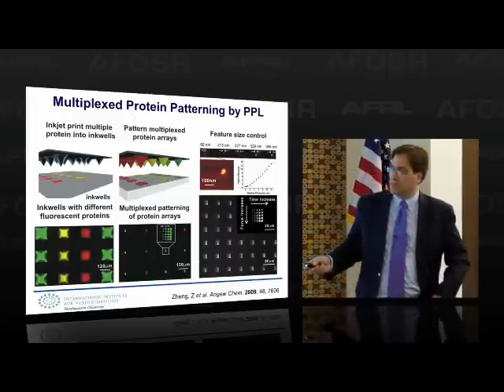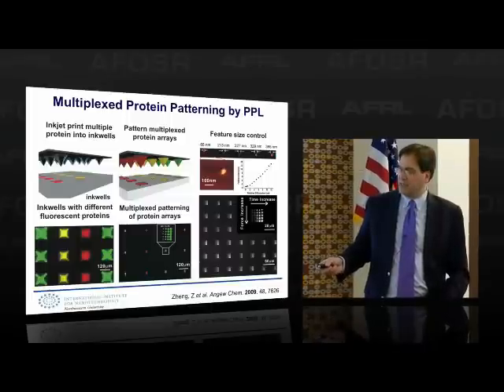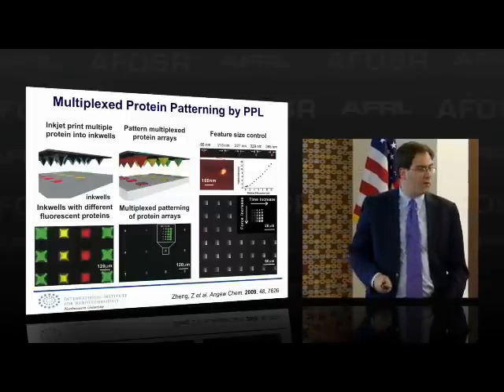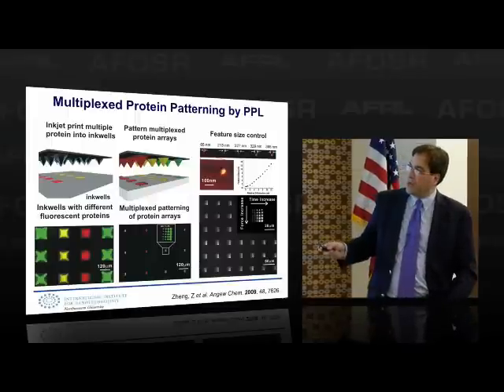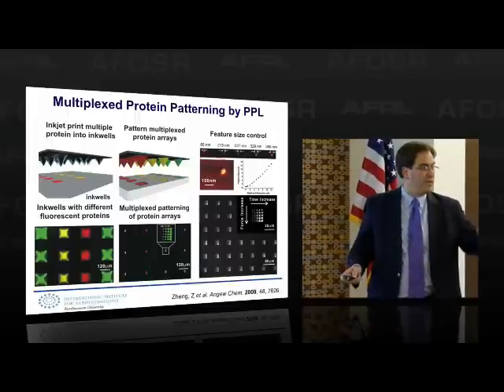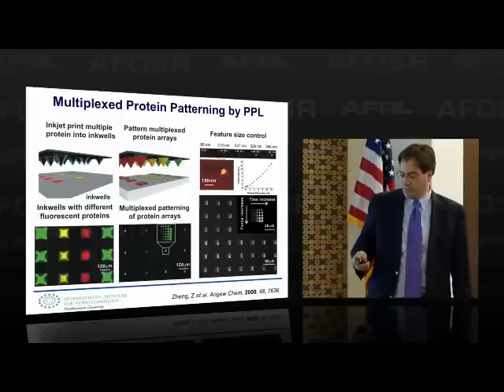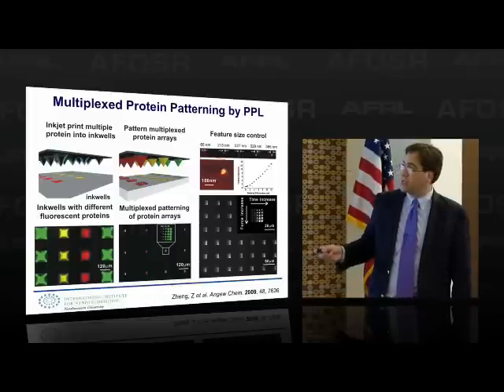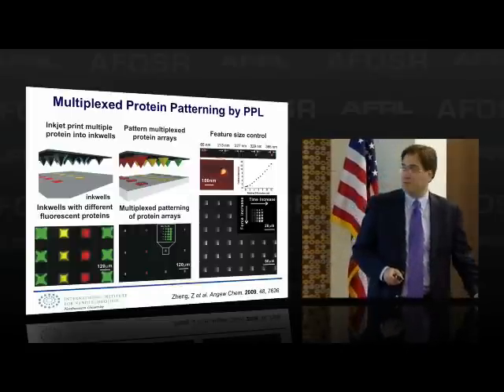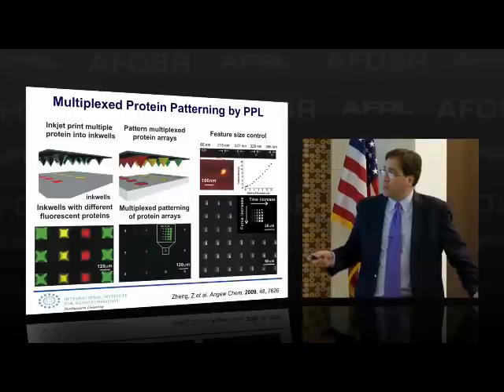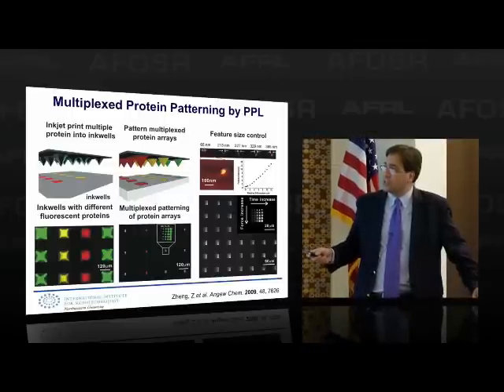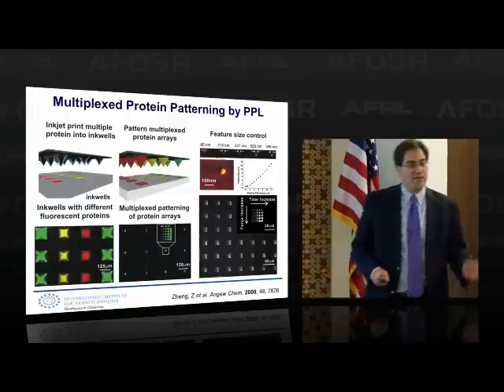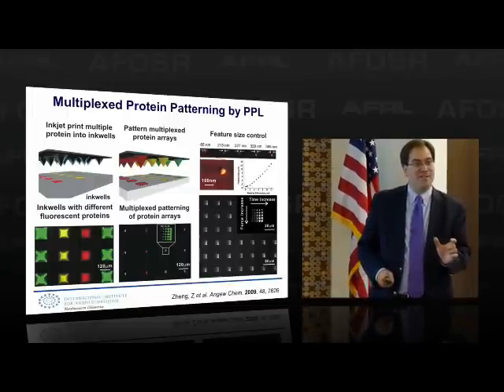We put dyes on proteins in this case, and even if you get a little splash, it doesn't matter because these are quite a bit away from one another. And now if I get 2 pens in, I have all 15,000 pens in. And so when I do this, I can coat the tips with different types of molecules. I can now bring the array down onto the substrate, and I can begin to pattern. Each of these are different protein structures, you can see by the different dye labels. And here you can see we can build an array that varies in feature size by controlling contact force.